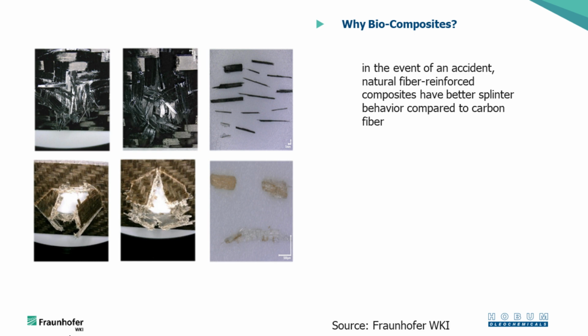That brings us to the next slide. Here you see some pictures from tests. Carbon fiber composites have been crushed, and also the natural fiber composite has been crushed, which is made in this case from linen fiber. And you can see pretty nasty splinters that come from the carbon fiber systems. And whoever has worked with carbon fibers and has seen carbon fibers breaking, these splinters really enter the skin and can make nasty injuries. So there's also good reason to maybe look at the natural fiber composites.